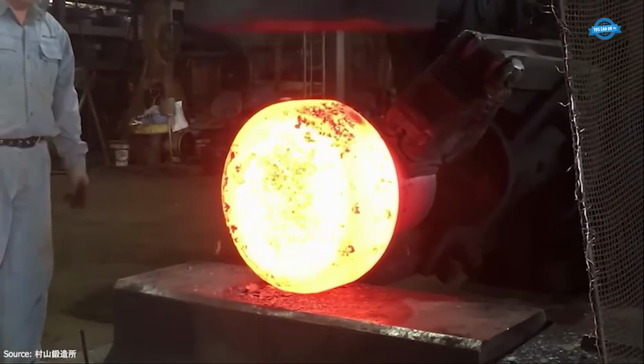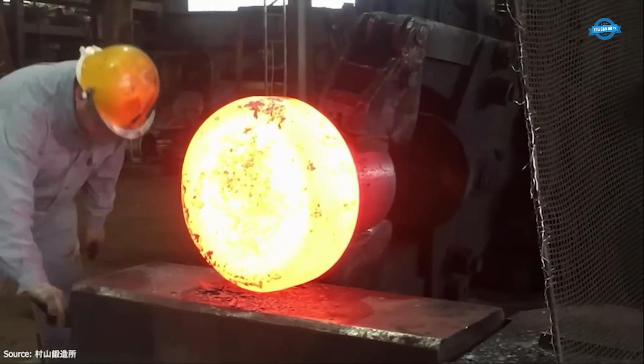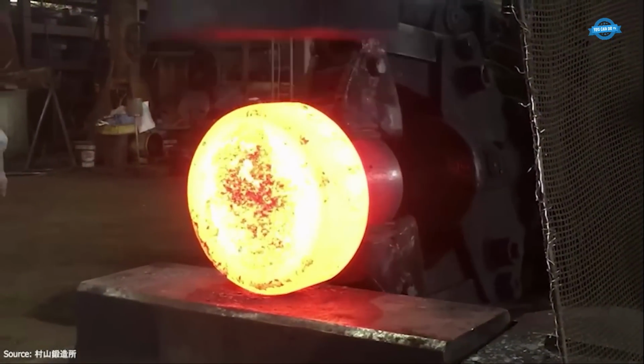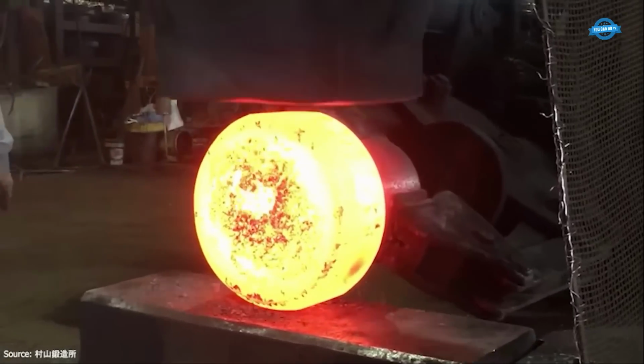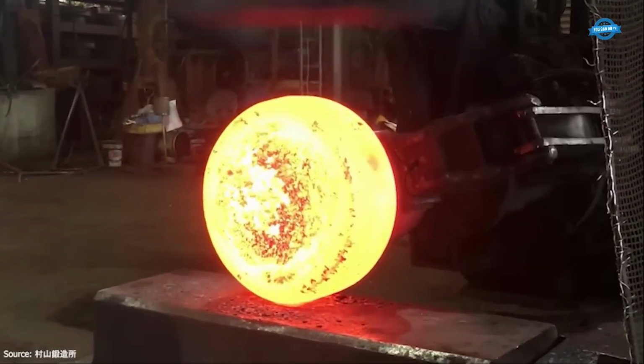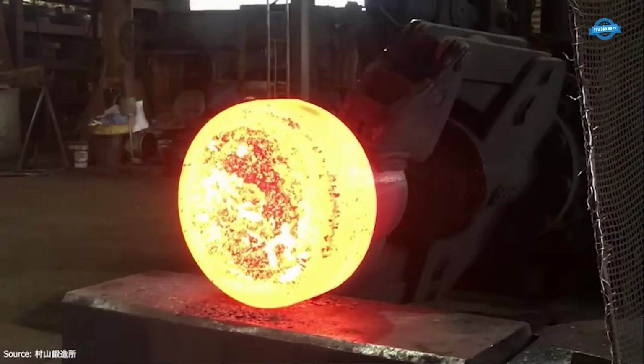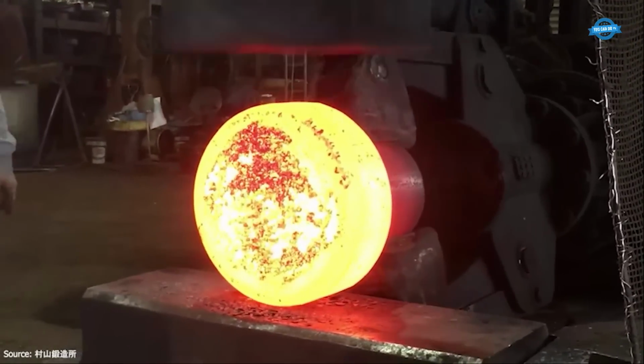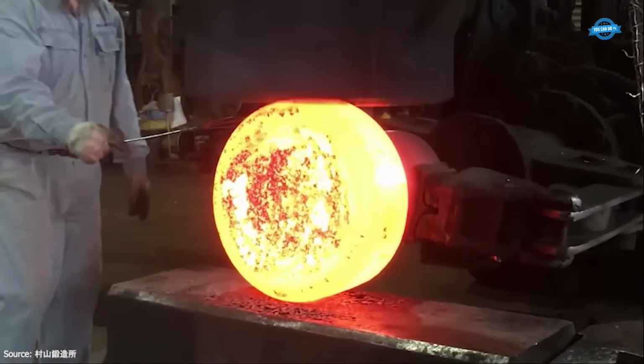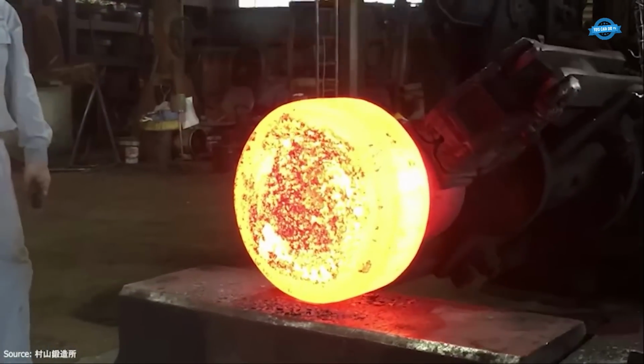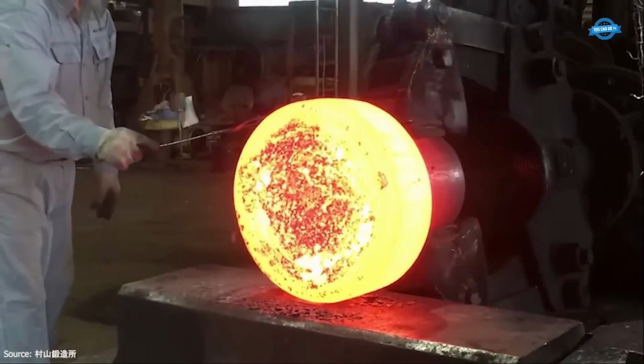Shaping of the piece continues with precision. The operator repeatedly compresses and elongates the billet, controlling the forging ratio, the ratio of the initial to final cross-sectional area, to achieve desired mechanical properties. Typically, a minimum forging ratio of 3:1 is targeted for critical parts to refine grain structure and eliminate internal porosity.